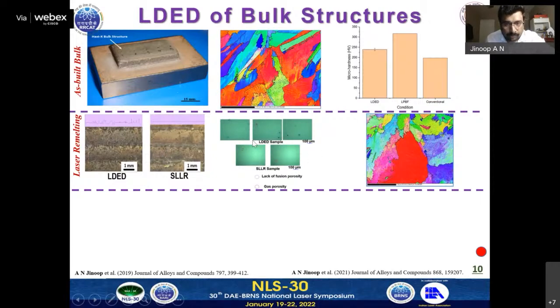And in case of porosity, we could see that in the as-built sample, we can see lack of fusion porosity, and the porosity is significant in the range of 0.5%, which is reduced significantly to around 0.01% with the application of SLLR. And the grain size was also refined, and we could see an increase in the mechanical properties by 12% and 7% in terms of microhardness and yield strength with the laser remelting process.